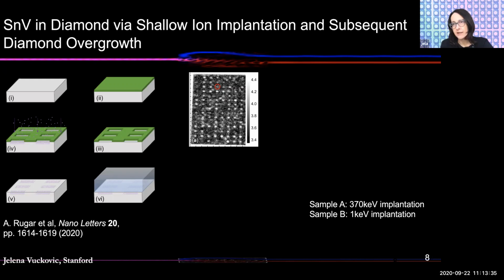We do that at 1 kilo electron volt as opposed to hundreds of kilo electron volts that are typically used for the process. And of course, that minimizes the damage of the lattice, but it also leads to color centers that are very close to the surface of diamond. And that's not really desirable for experiments. So what we have to do is regrow a high purity layer of diamond on top of the structure at the very end of the process. And here you see resulting structures.